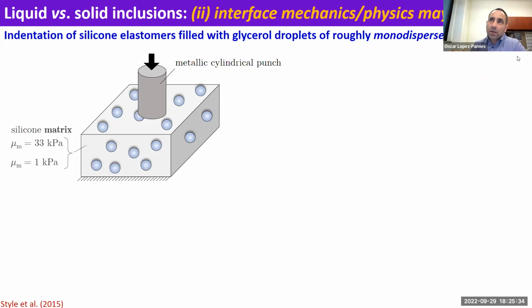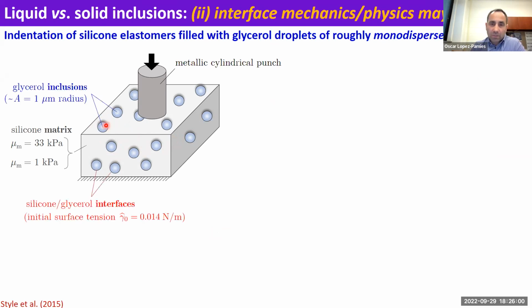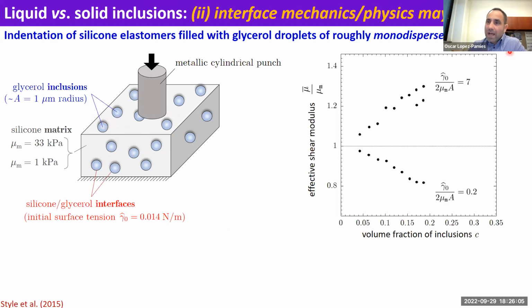The other aspect that is perhaps even more interesting is that when you have a fluid inclusion, you have to think that you may have interface mechanics. Think of surface tension, that it may play a role. In fact, there are experiments recently that show that interface mechanics for some systems with liquid inclusions control the entire mechanical response. And this is just one example. In this case, the matrix is silicone. These inclusions are glycerol, which is some sort of polymer, but it's a liquid. And let me just show you what happens.